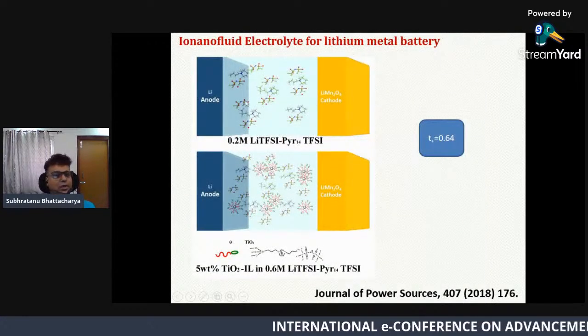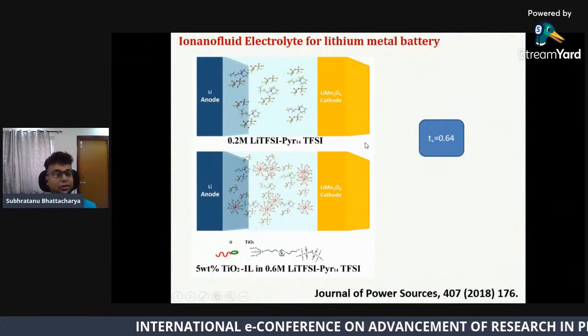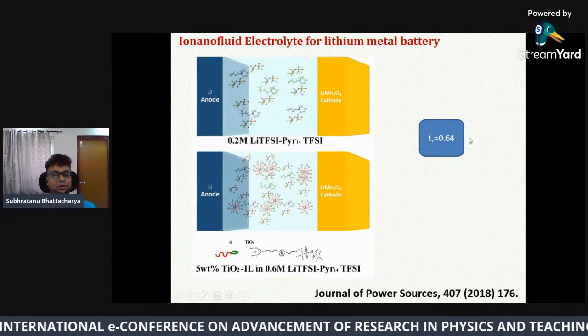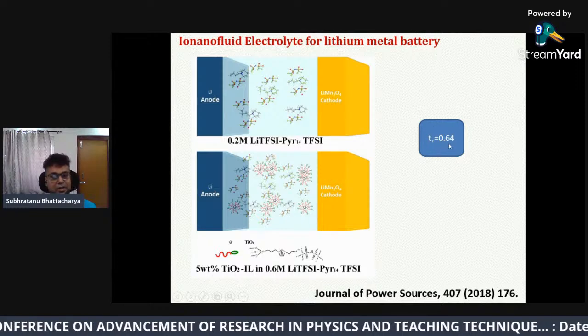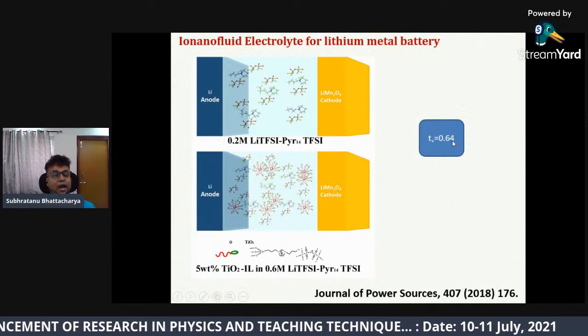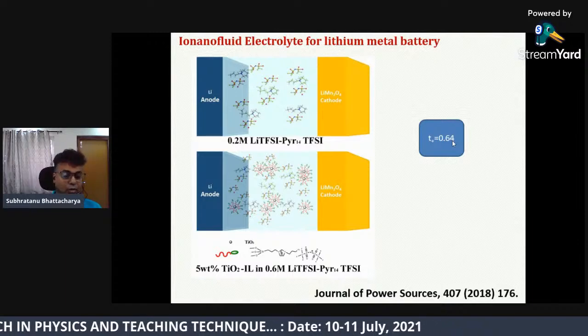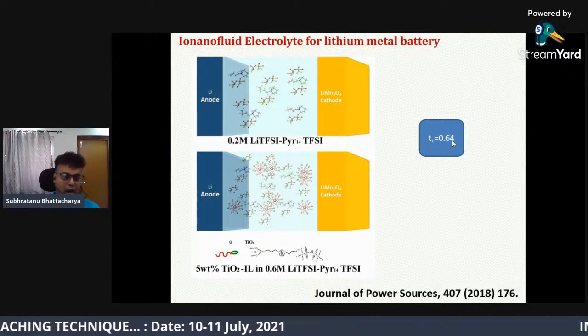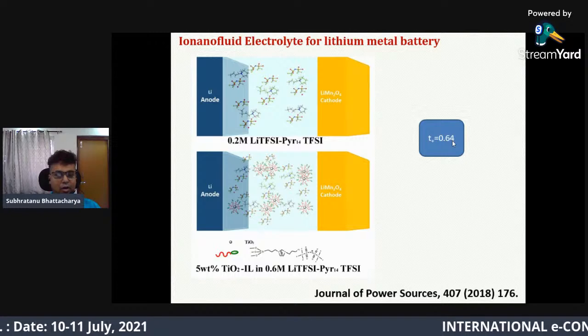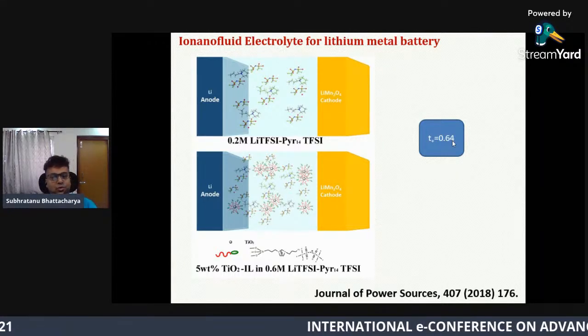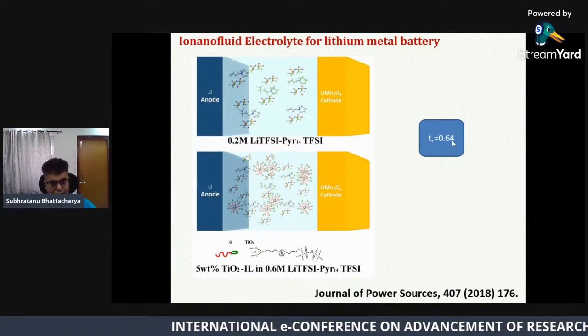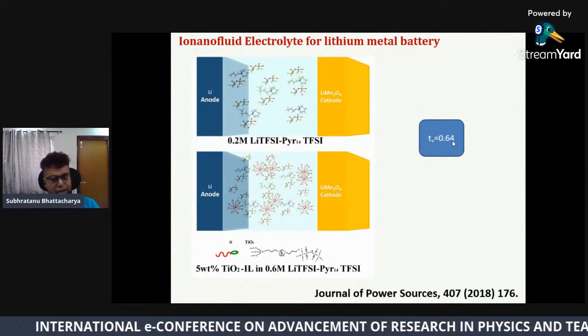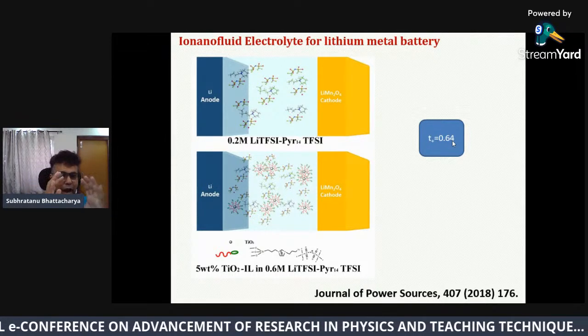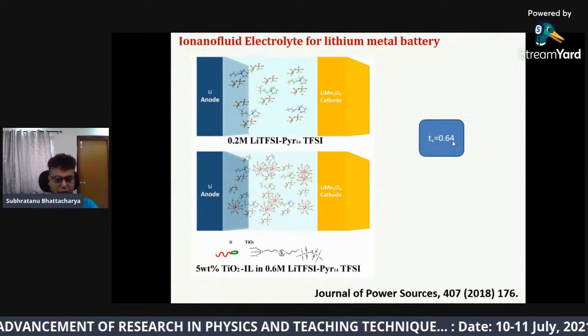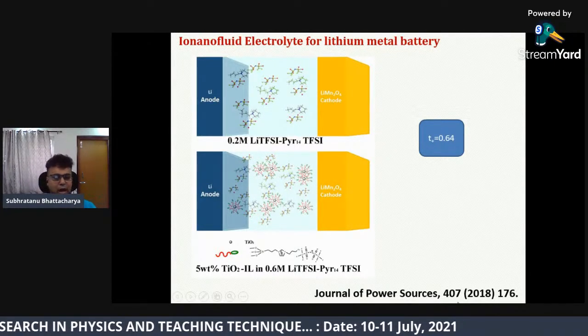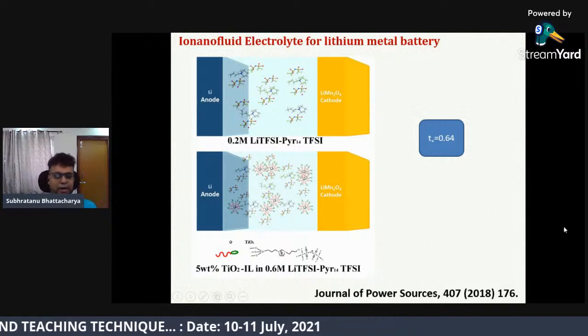And we have used it in the lithium battery, and we get very high quality battery performance with a lithium ion transference number around 0.64, which is very high considering that for carbonate solvents the t plus value is only 0.23 in conventional electrolyte solvents. So instead of 0.23, we got 0.64 in the ionanofluid based electrolyte, and that is published in a very high quality journal.